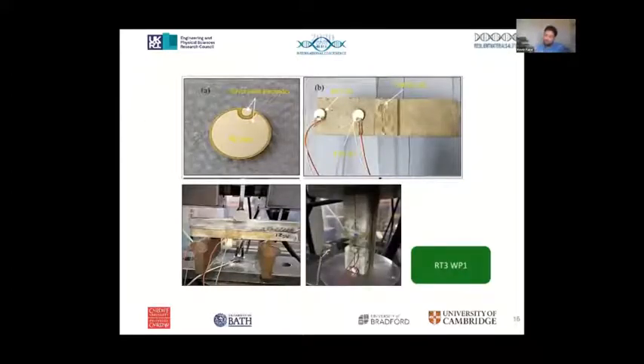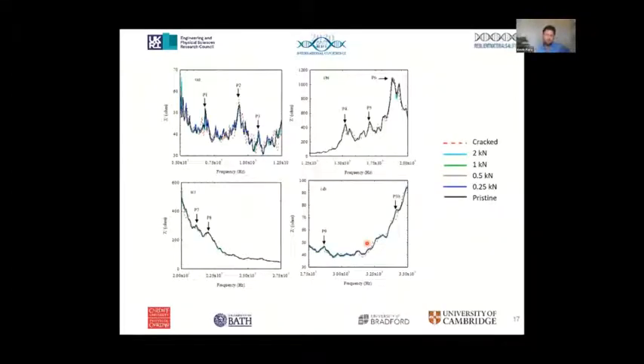This slide shows typical piezo sensors and how we attach these to the concrete externally. We then crack the concrete, and if necessary, we can also simulate healing by using compression. As we load the specimens, we then measure the impedance response as it changes from a pristine stage, as shown in black, to a crack stage, as shown in red.